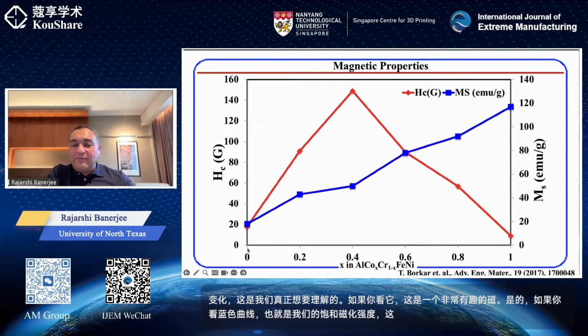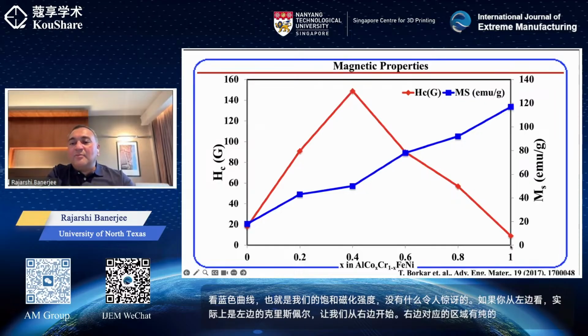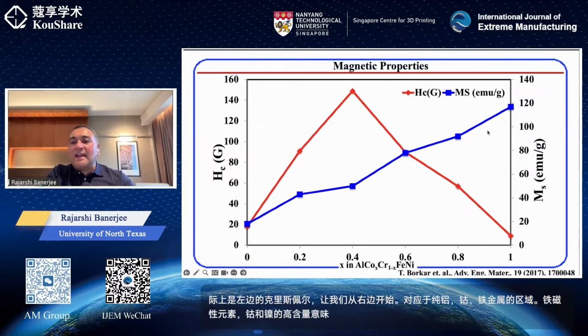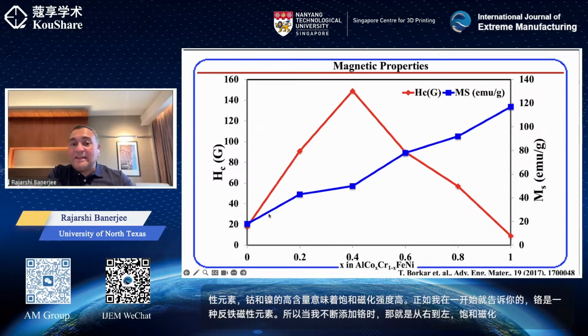If you look from the left, actually, let's start from the right. The right corresponds to the region which has pure aluminum, cobalt, iron, nickel. The high amount of ferromagnetic elements, cobalt, iron, nickel, means that the saturation magnetization is high. As I told you right in the beginning, chromium is an antiferromagnetic element. So as I keep adding chromium, that is going from right to left, the saturation magnetization is very nicely, systematically decreasing.